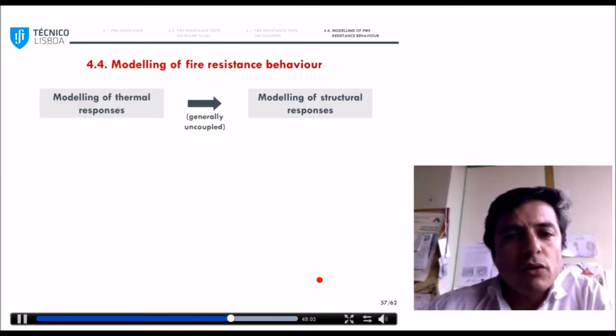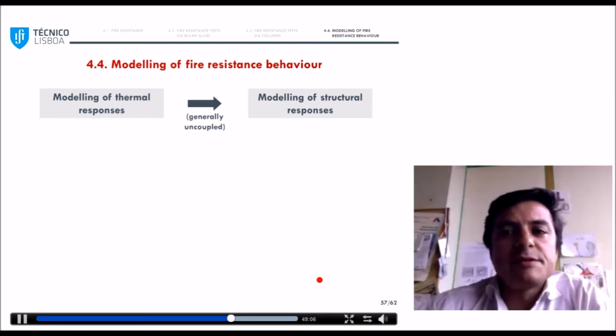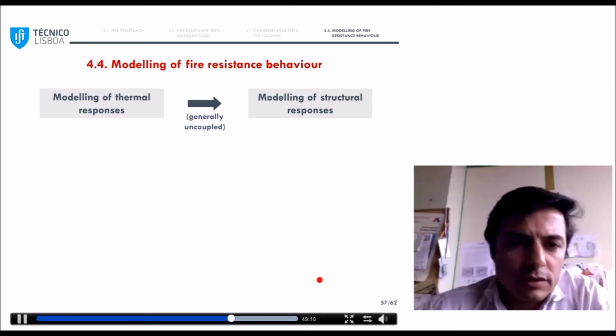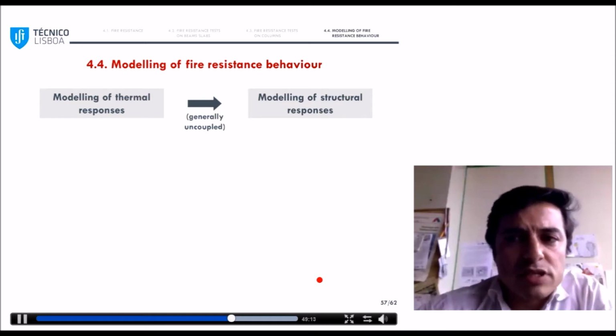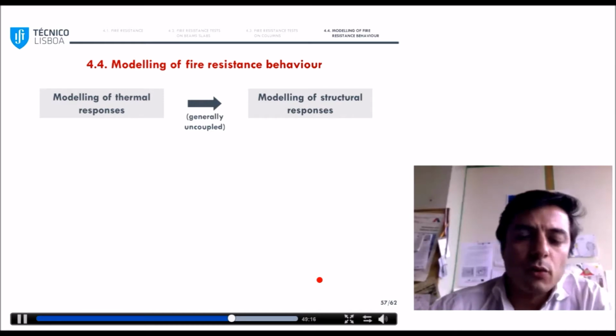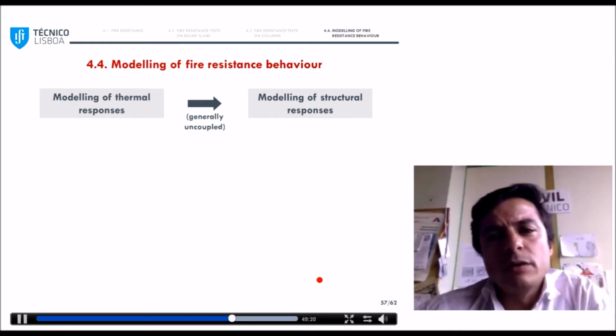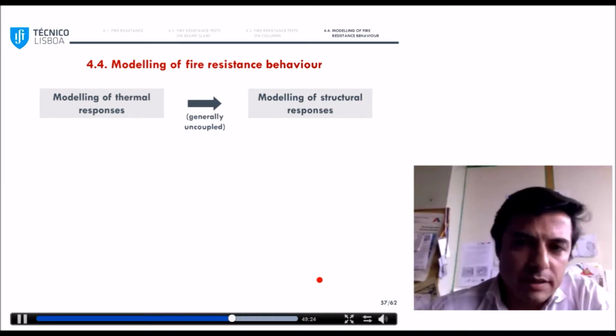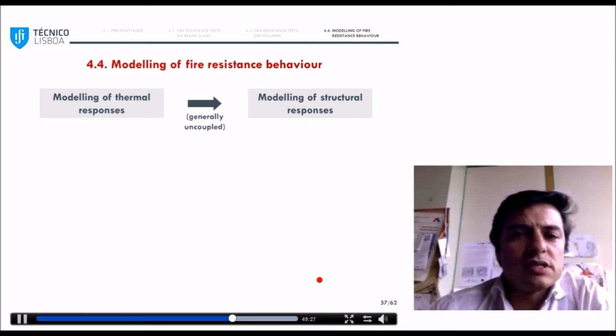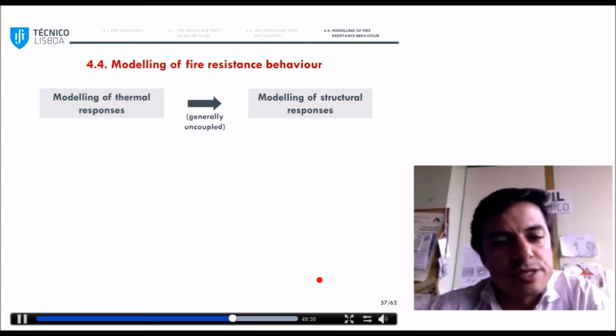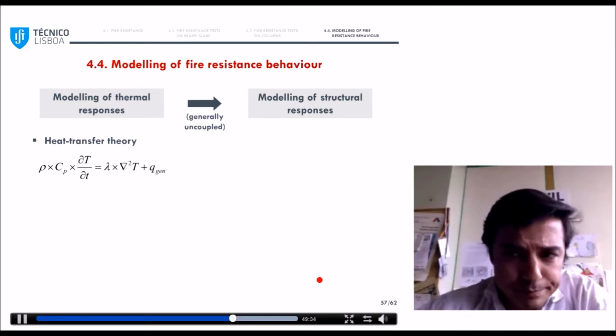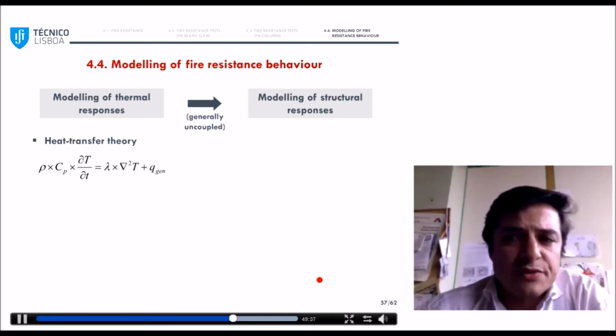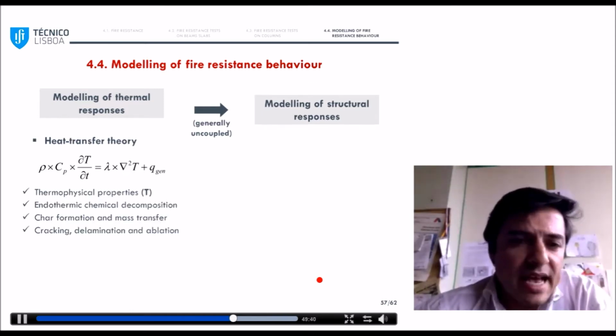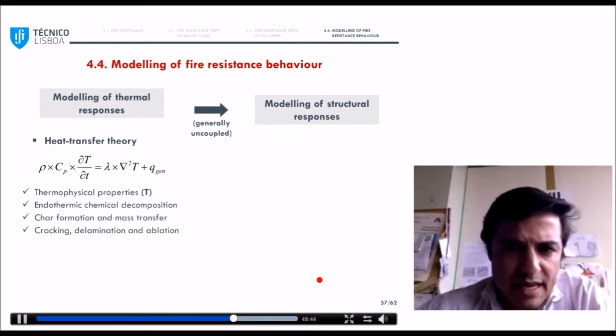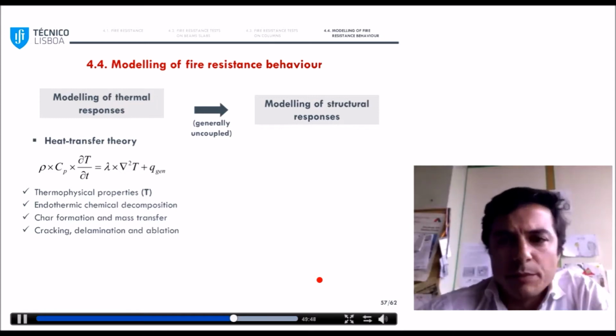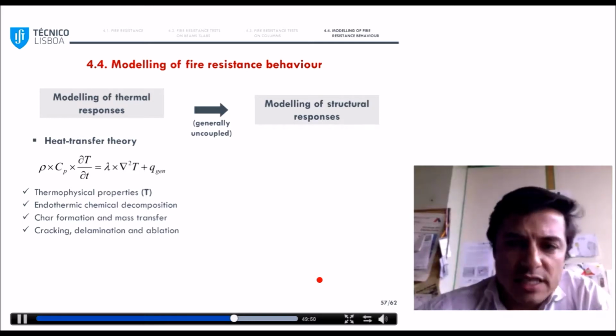So now about the modeling of the fire resistance behavior. This is a quite complex issue, so I will try to keep it as simple as possible, to give you an overview of the work that has been done in this field. In general, most colleagues have been following an uncoupled approach in which the thermal response is modeled first and then the structural response. The first step basically comprises applying heat transfer theory, considering different aspects: the temperature dependence of thermophysical properties, the endothermic decomposition of the resin, char formation, mass transfer, and different degradation mechanisms.